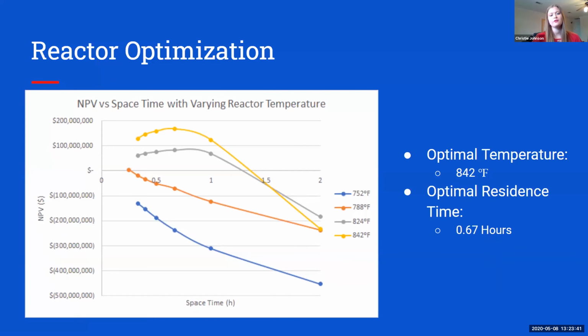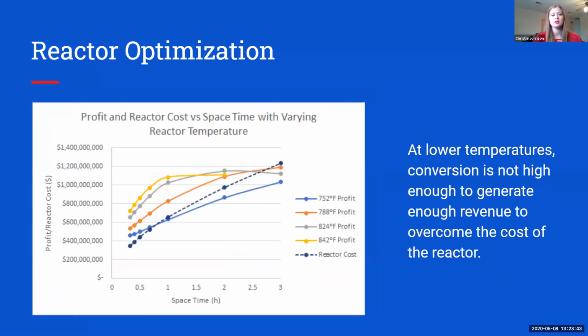And we would have liked to test higher temperatures to see if we could get that NPV up just a little bit more, but due to the limitations of our kinetic data, that was the highest temperature we were able to test. However, we would suspect that once you started to get the temperature too high, you would overcrack those valuable diesel and kerosene products into naphtha and gases, which are less valuable, and the revenue would begin to drop.